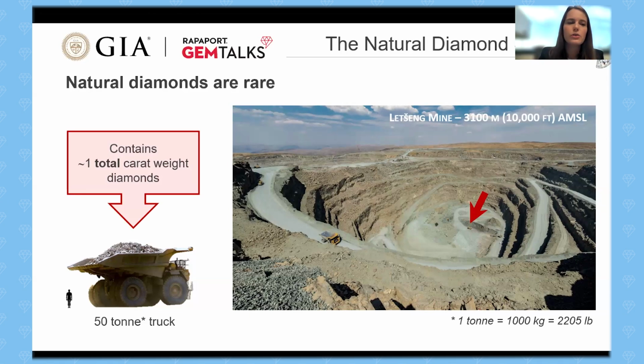And this grade is going to vary from mine to mine. This is Letseng, which is known for having a very low grade, but very valuable stones coming out of it, whereas most commercial mines average about 0.3 to 1 carat per ton. I.e., that means that this 50-ton truck could potentially contain about 15 to 50 carats of total weight of diamonds, but this is going to be mixed quality. And then out of those, only about 30% of the diamonds recovered are actually gem quality.